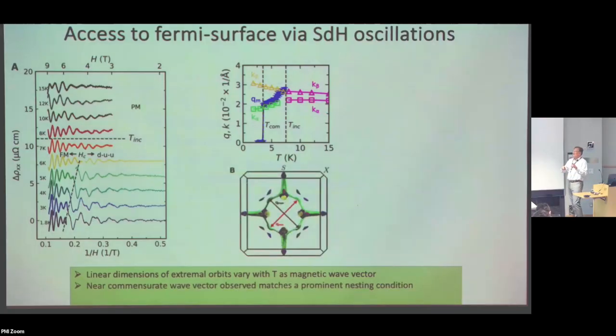Okay, so now we want to make connection to the band structure calculation, and so shown here is the Fermi surface calculated by Vanderbilt and his group, and then I've overlaid on that two wave vectors that are very close to the measured wave vector for the magnetic order that we observe. We define specifically a minimum and a maximum wave vector, and they end up bracketing the actually observed wave vector for the magnetic order. They have the same directionality as the observed wave vector, and the observed wave vector lies in between these two, as I'll show in a bit.